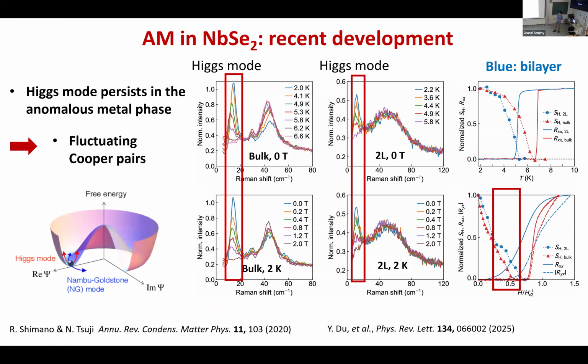And first of all, what they measured is they use Raman spectroscopy, but they cool down to very low temperature into the superconducting state. And within the superconducting state, they see a mode appearing, which is related to the Higgs mode, so the amplitude mode of the order parameter. And this is in the bulk. You can see that either you increase temperature to about the critical temperature, this mode disappears, or you increase the field to kill this mode. So this is related to superconductivity. And for the bilayer case, the interesting thing is, if we apply some small field, you go into the anomalous metal phase, do we still see the Higgs mode or not?